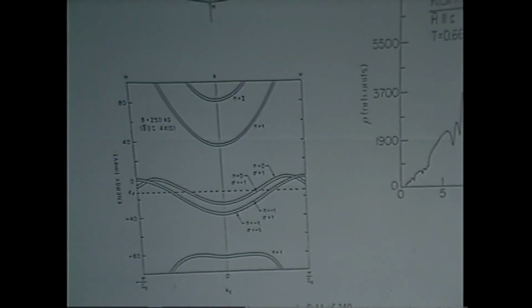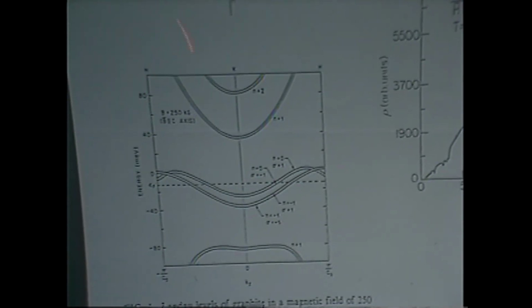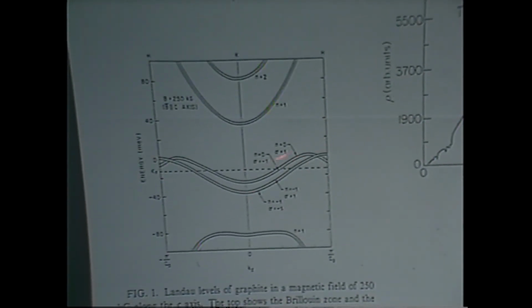Very, very surprising. Well, the explanation, or one explanation, maybe not the final explanation of this, is that you have a charge density wave instability that's set up, because these bands here that you see, they're sort of cosine bands, and they're half filled.